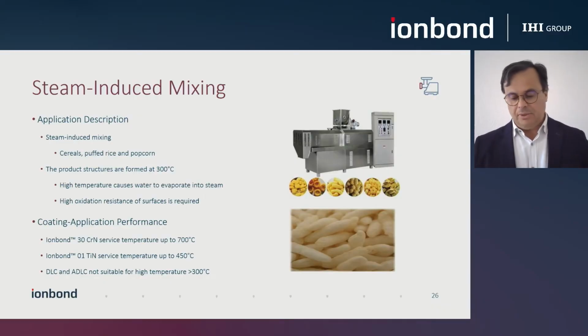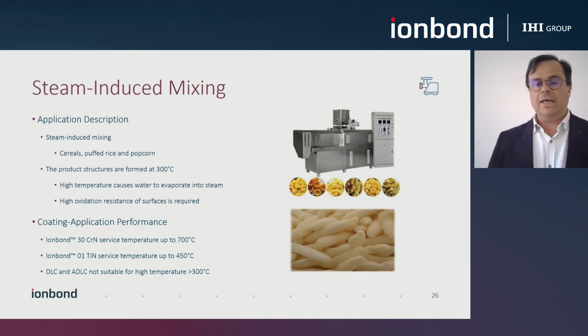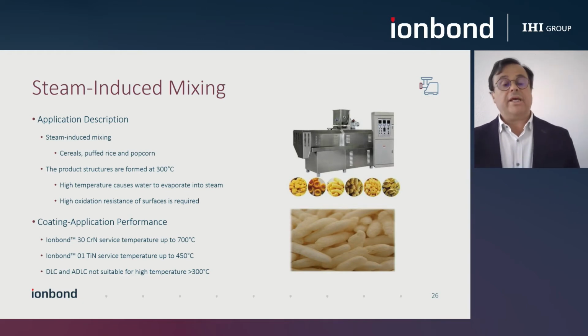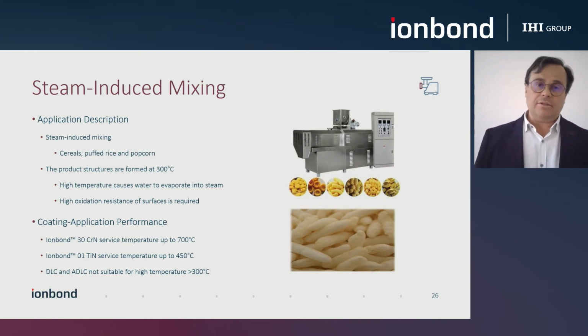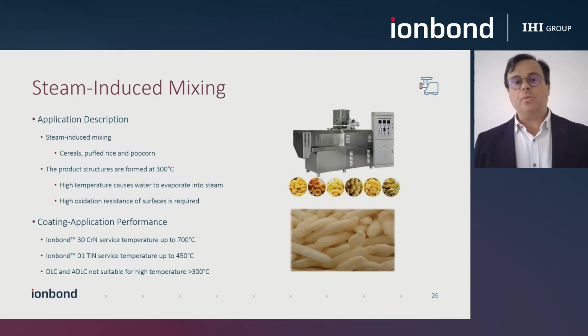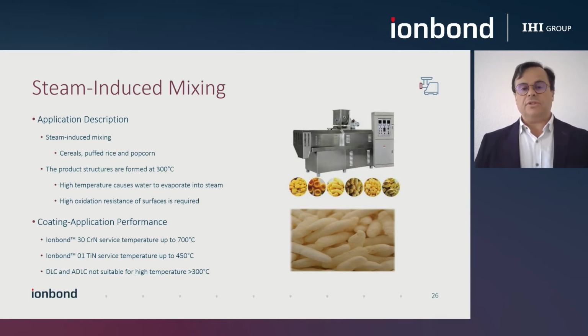You can use titanium nitride, which is completely stable up to 450 degrees C. Also chromium nitride, again, up to 700 degrees C. In this particular application, we do not think that diamond-like carbon can perform so well, as we see some tendency for structure change or loss of properties above 300 degrees C.